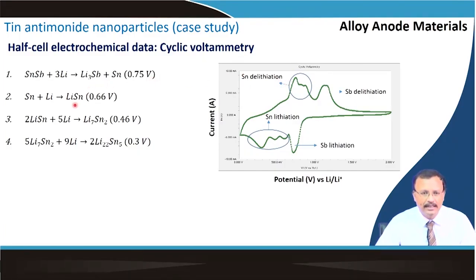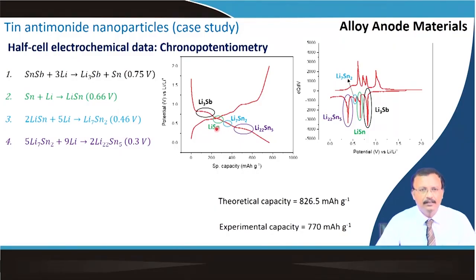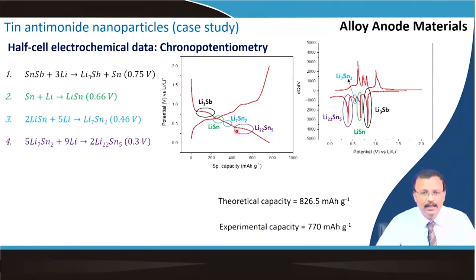Whether it is really Li₃Sb, LiSn, or Li₇Sn₂ — to identify these phases you stop the measurement at that specific voltage, take out the electrode, and do X-ray diffraction to confirm whether you are getting those phases. Similarly, charge-discharge measurements show a stepped structure in line with the theoretical estimation. The differential capacity plot (dQ/dV vs. potential) differentiates the curve and very precisely identifies the voltage at which each phase forms.